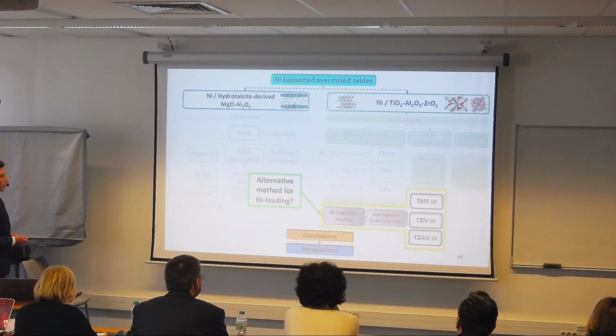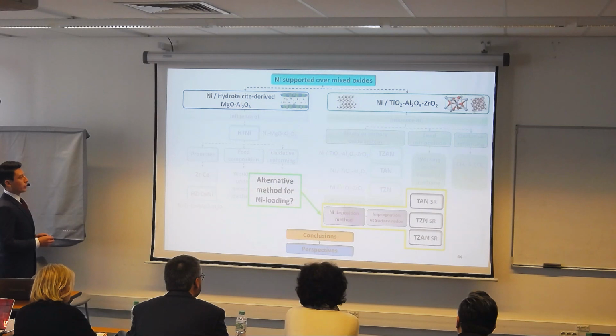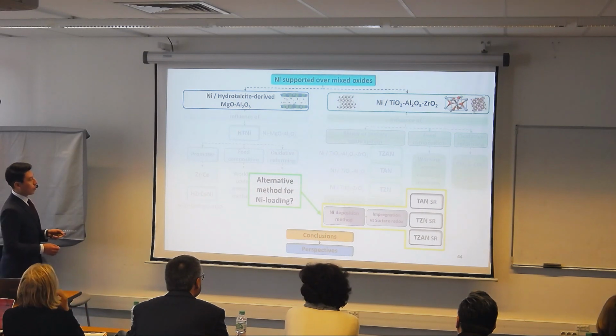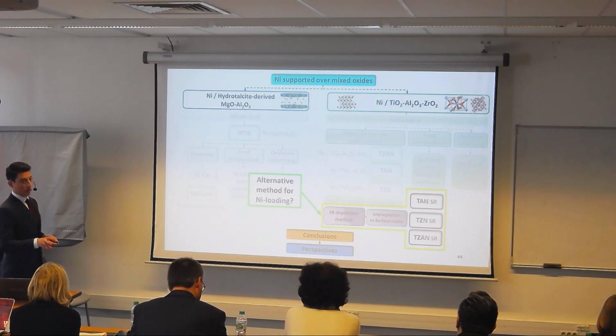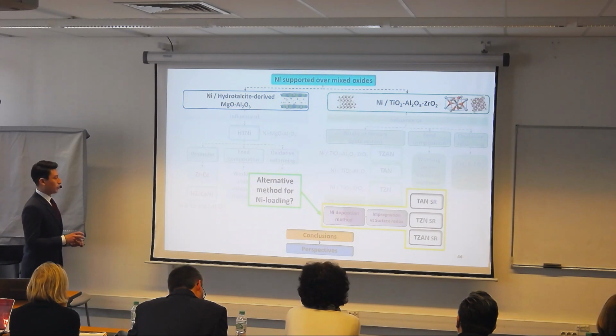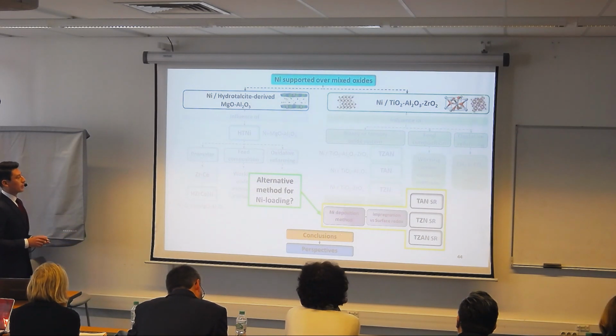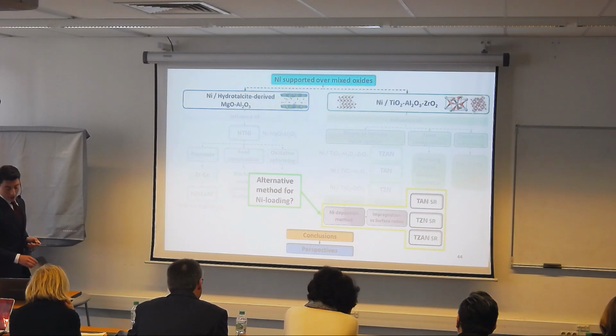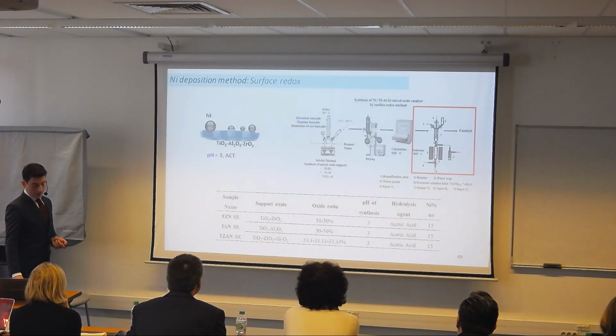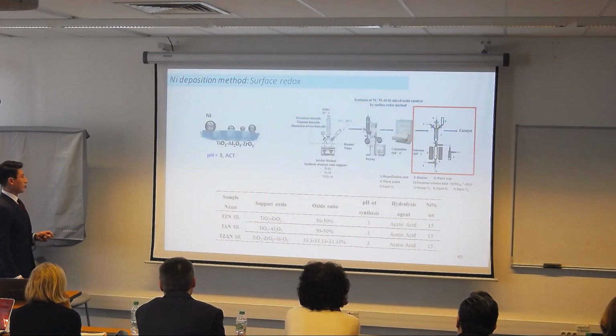We were thinking of another alternative in order to enhance the behavior, so we propose another method of depositing the nickel onto the support. In this part, I'm going to present the surface redox method, with another series of catalysts to test. We use the same binary and ternary systems as in the beginning, at a pH of 3, but now the nickel was deposited by the surface redox method.